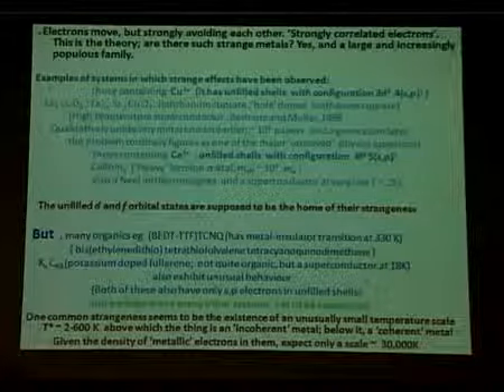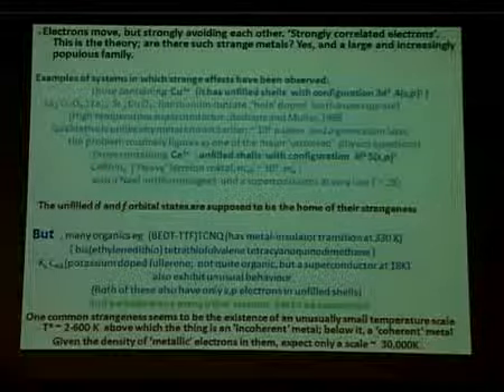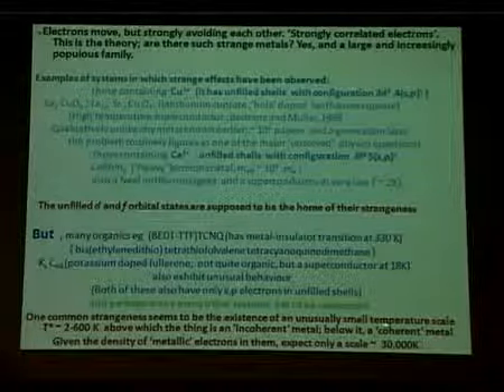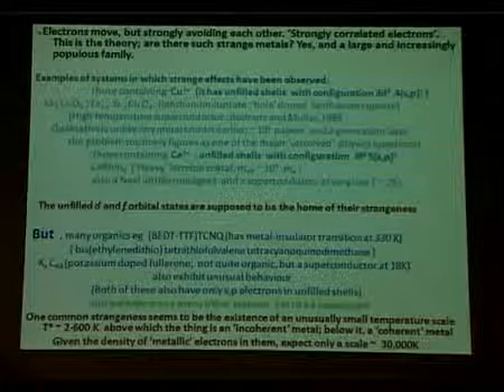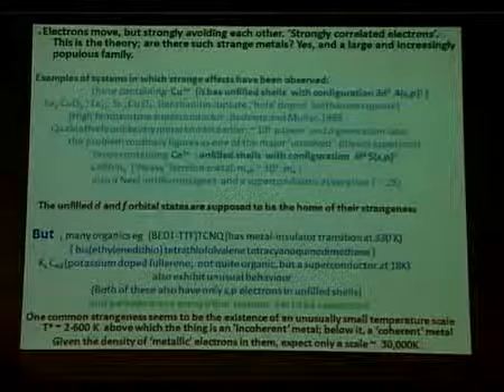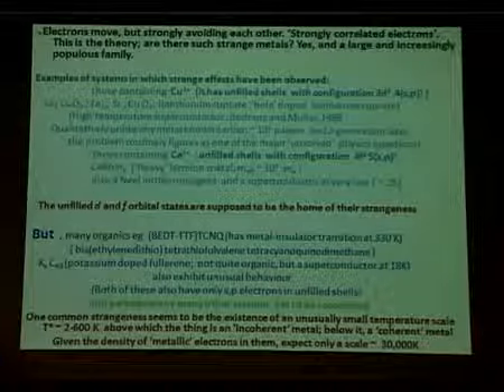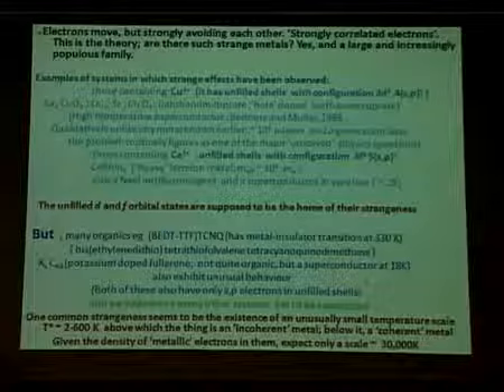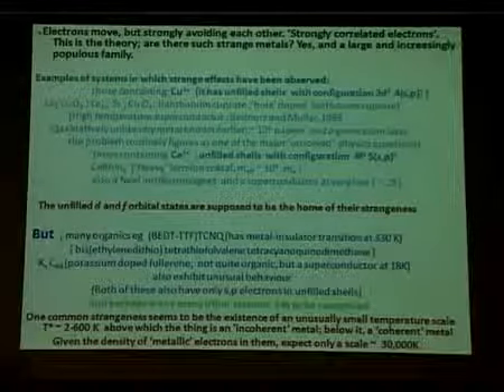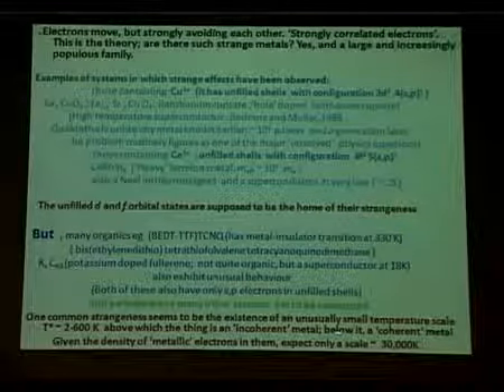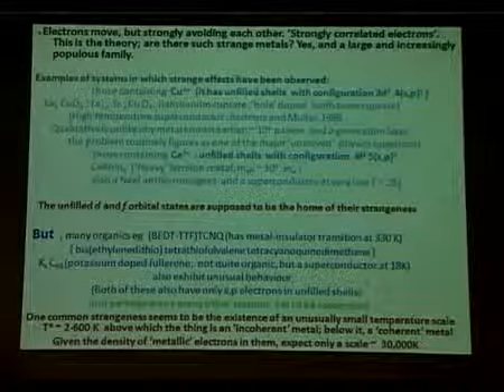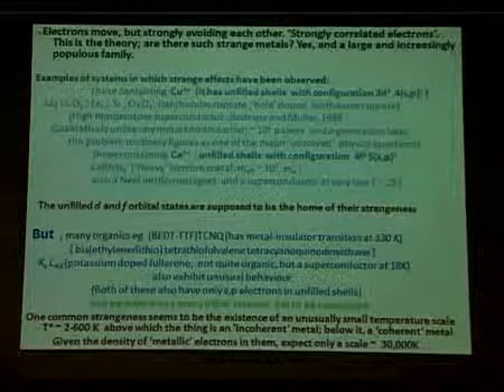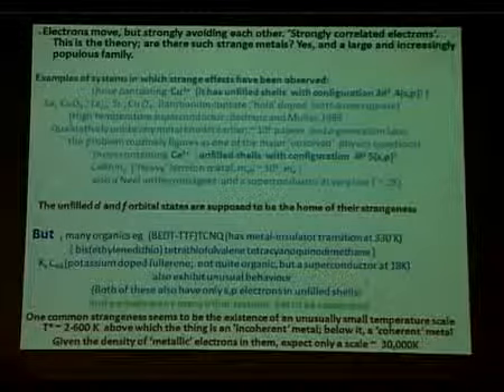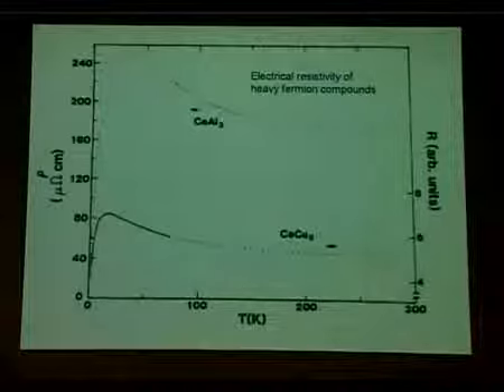Okay. That seems a little vague, but let me say that there is one common strangeness, which is that in these systems there seems to exist a very low energy scale. This low energy scale is of the order of 2 to 600 degrees Kelvin. Above this energy scale, the thing is still a metal, but it's an incoherent metal. It's a bad metal. Below that, it's a coherent metal. Now, why is this temperature scale unusual? It's unusual because, given the density of metallic electrons in them, we expect a scale of the order of 30,000 degrees Kelvin. So nothing should happen at 200 or 300 degrees Kelvin, but it does. That may be the defining feature of these systems.